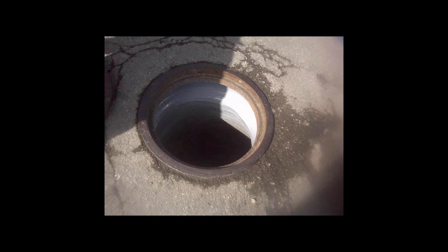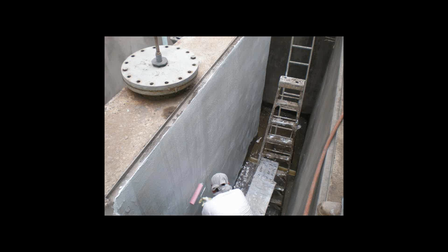That's a completed manhole with an epoxy coating. Another epoxy in a wet well. Nice epoxy coating in headworks. This particular manhole, although the picture is not the best, had complete aggregate showing, and there's 250 mils or 1/4 inch epoxy in this structure that brought it back to life, extended the life per se.